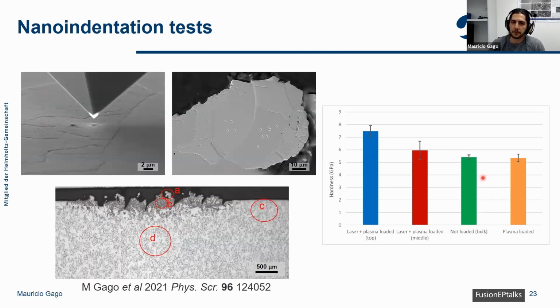And lastly, the hardness of the sample surface was tested after tests with the highest power load. So this was to see how hardness is affected by a combination of both loads. And we can see that at the top of the sample here, the hardness increases significantly. And then underneath the surface, some micrometers underneath, we still see the effects of the increase in hardness. And then it gradually decreases until we reach the bulk of the sample, where the hardness stabilizes, basically.